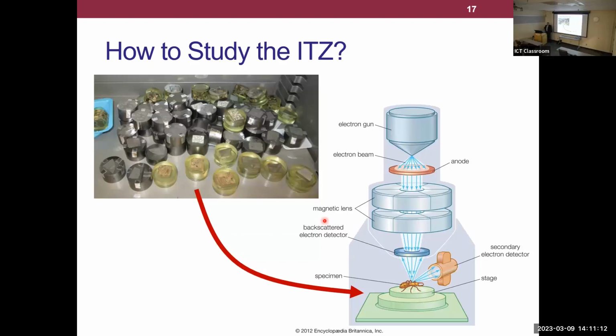Sample preparation is really difficult. You have to take your concrete, dry it out, and backfill all the pores with epoxy to stabilize the microstructure. Then you have to polish it really flat, and then you can put it in the electron microscope. That process alone took me 6 months of my PhD. But once it worked, we were able to get a lot of data. So anyways, that's what we did.